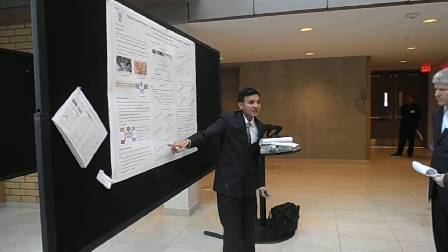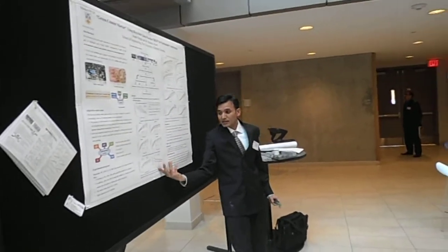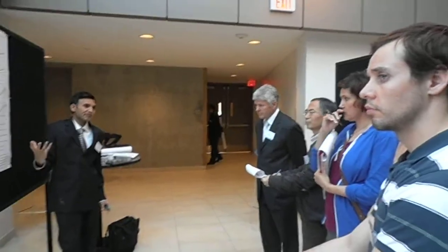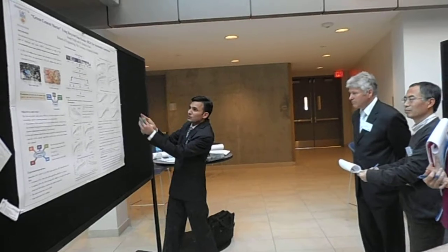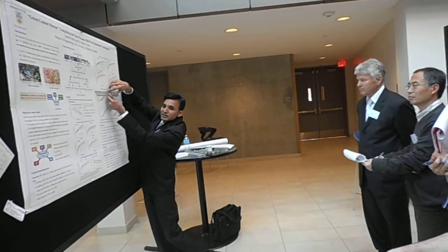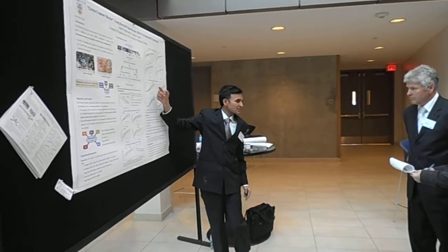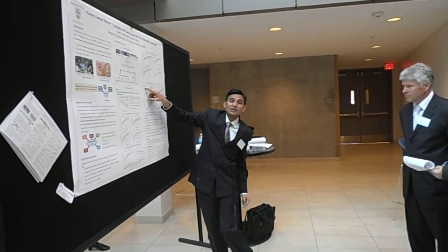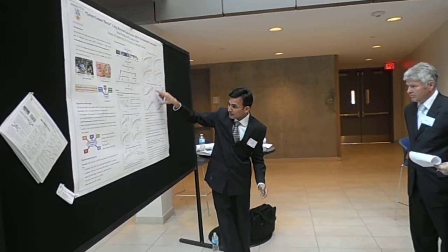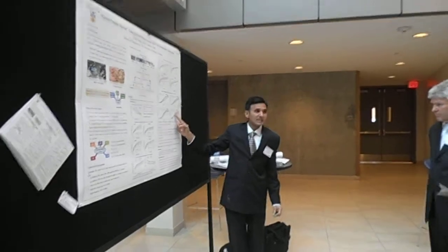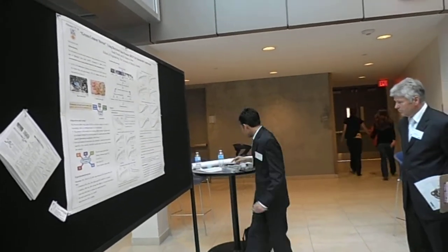In physical properties, bulk density is increasing and water absorption is reducing, which is very good. For the alkali silica reaction, the expansion is low, below 10%, which is desirable based on the American standard ASTM 1260. Below 10%, there will not be any adverse effect on the concrete. We found that mix D is the optimum mix proportion, so 25% glass is better.